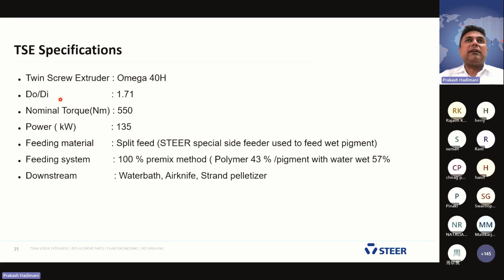Now we are discussing the case study. We have used a twin screw extruder, Omega 40H class, with a Do/Di of 1.71. Because it had 60% water, we selected a Do/Di of 1.71. The reason is that you need higher free volume so that it can withstand more water, the material will be discharged better, and dewatering will be done faster. The nominal torque is 550 Newton meter, and power is from a 135 kilowatt motor.